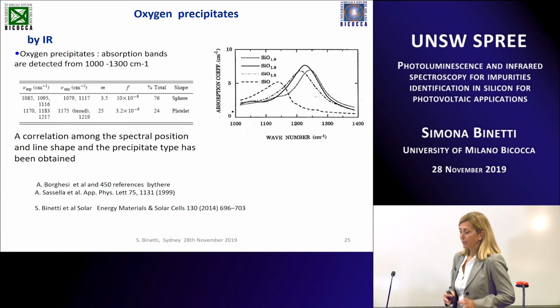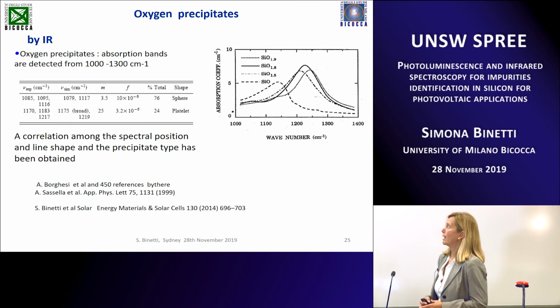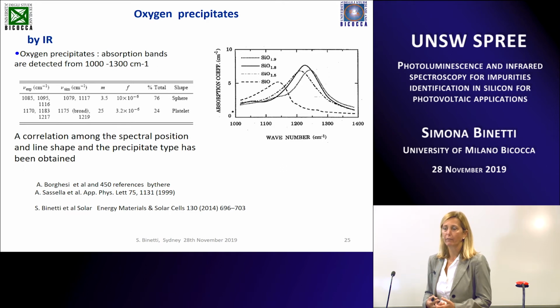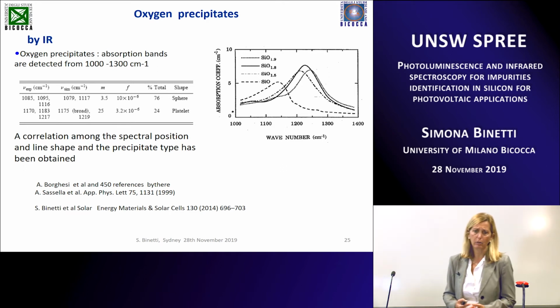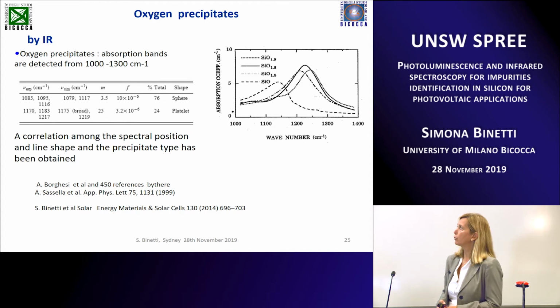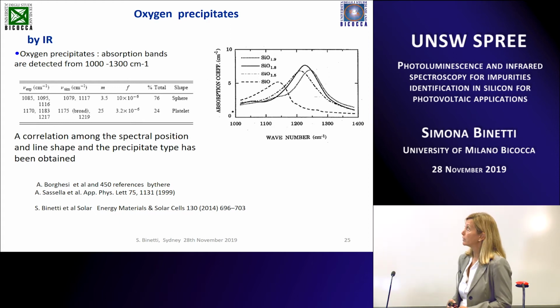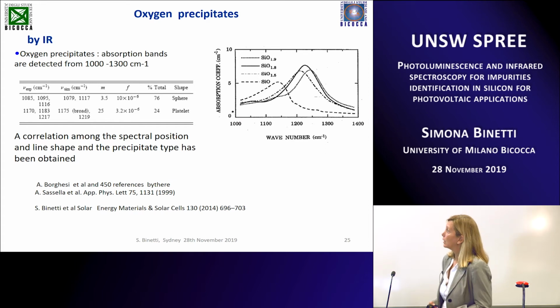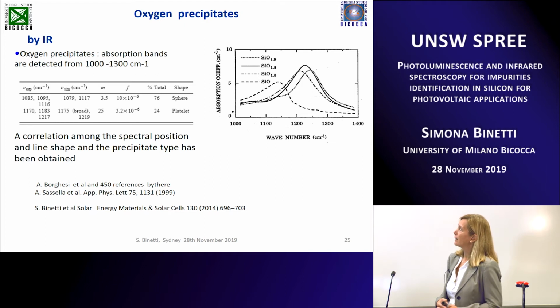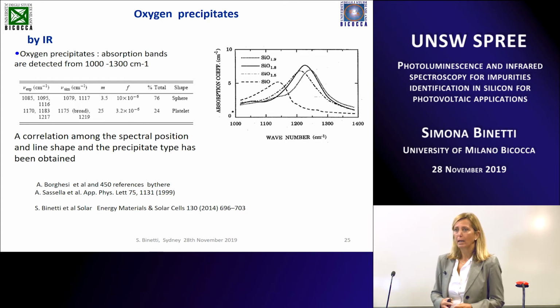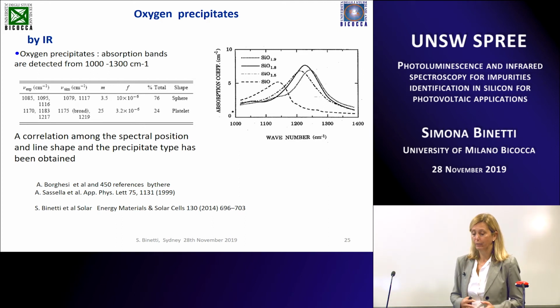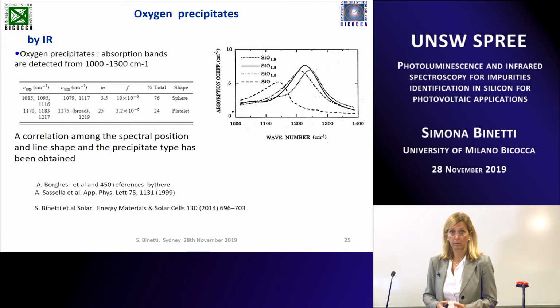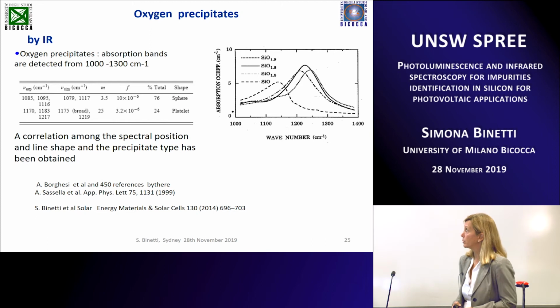So we have seen the early stage, the thermal donors, and then you can have quite large oxygen precipitation after several thermal annealing processes, which is not standard in the case of silicon for photovoltaics. But if you have large precipitates, you can detect these precipitates also by infrared measurement at low temperature, but sometimes also at room temperature, as I will show you. According to the shape and the position of this band, you can also determine the type of oxygen precipitates, and also the stoichiometry of oxygen precipitates, as reported here.